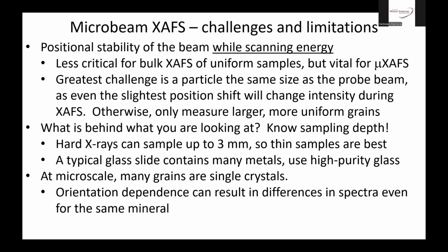Thin samples are best, but even thin samples, a classic thin section is 30 microns. So you're still seeing 30 microns of material with the beam. Also, what it's mounted to is important. A typical glass slide that you might have a rock thin section mounted to has half the periodic table in it. So you need to use high purity glass. Otherwise, you'll be seeing all sorts of things that are not in your sample. And finally, at the microscale, many mineral grains, or different materials as well, are single crystals. And so the orientation of a single crystal relative to the polarization of the X-ray beam can change the shape and structure of spectra. So you have to take that into account, or at least be aware of it.